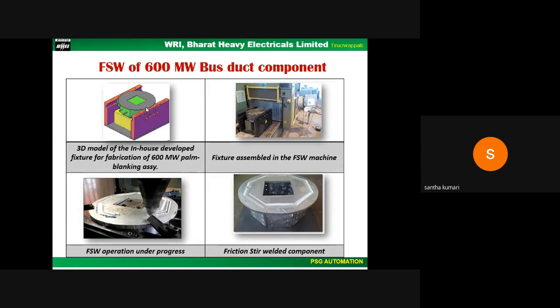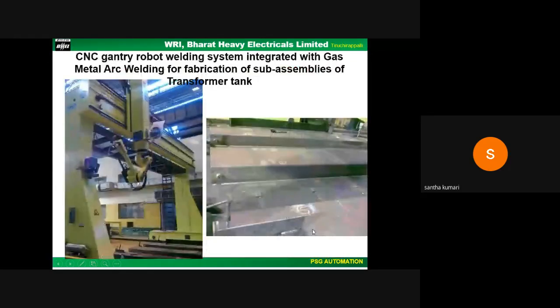Fixture and tool is a major development that had to be done for friction stir welding of this component. So to automate this welding, we had to develop the fixture and tool to guide the CNC for the continuous friction stir welding of an octagonal aluminum bus bar component, which reduced distortion of the welded component, and it also got qualified in UT. So this level of automation has gone into our boiler components.